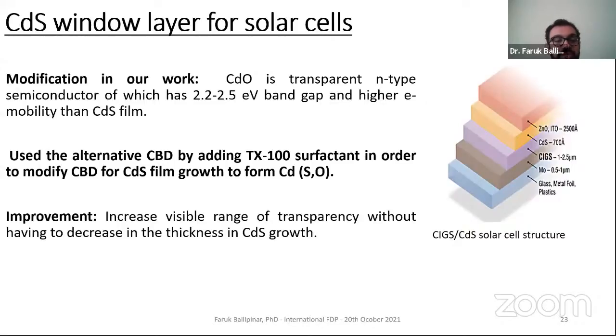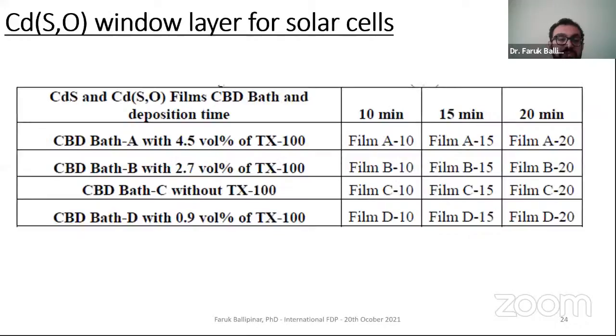So what was the main improvement? I'll share the result in the following slides. There was an increment in the visible range of transparency without any decrease in the thickness of CdS growth. We have definitely the same thickness for CdS and CdSO, but there was an incredible increase in the visible range. There were 3 setups in terms of deposition time. Basically, it only changed the thickness of the film: 10 minutes, 15 minutes, and 20 minutes.